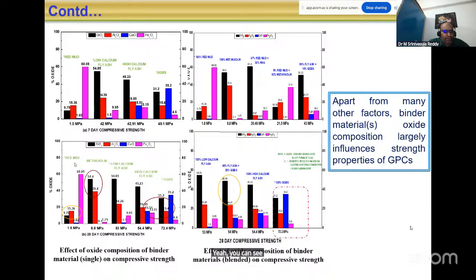Yeah, you can see here the effect of oxide composition on the 7-day compressive strength and 28-day compressive strength. With red mud alone, very little. With fly ash alone, this much. With high calcium, this much. With GGBS alone, this much. And you can see here in the combination. These are all based on calculating the amount of oxides present in each waste material or industrial binder material. So you will get good strength only when it is in this range.